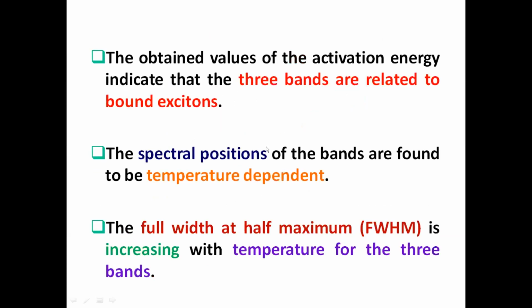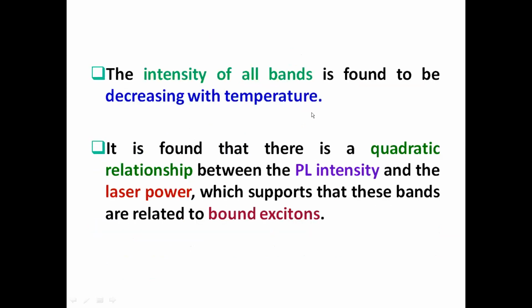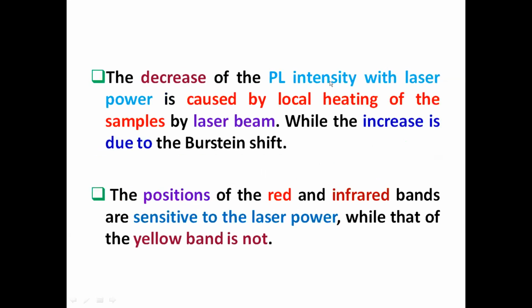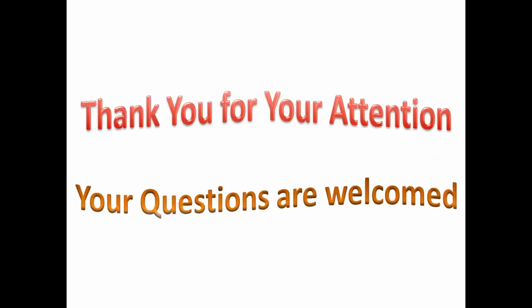Now, spectral positions are found to be temperature dependent. Full width at half maximum also depends on temperature. The intensity of all bands decreased with temperature. A quadratic relation was found between PL intensity and laser power, which means that these bands are related to bound excitons. The decrease is related to laser heating. Now, thank you for your attention.